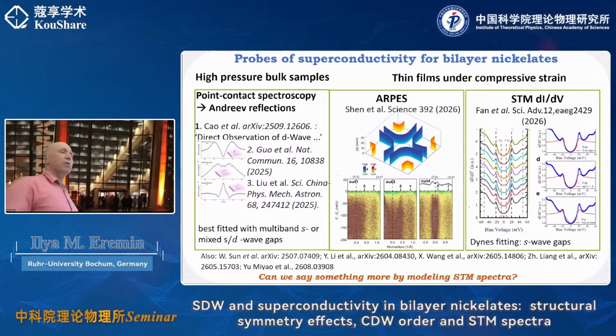One could in general put a grain of salt on all these measurements, because if you look at the data, you will see that the enhancement of the signal is only about 10% of the total signal. And that tells you that these junctions are in a strongly diffusive limit, and the theory analysis that has been done, of course, has been done in a clean limit. That raises the question: how reliable are conclusions if you use formulas which are strictly speaking valid in a clean limit for a junction which is in a strongly diffusive limit? But nevertheless, there is some ambiguity. And now ARPES at this point tells us it's very likely an S-wave-like gap. And now the data start to converge.